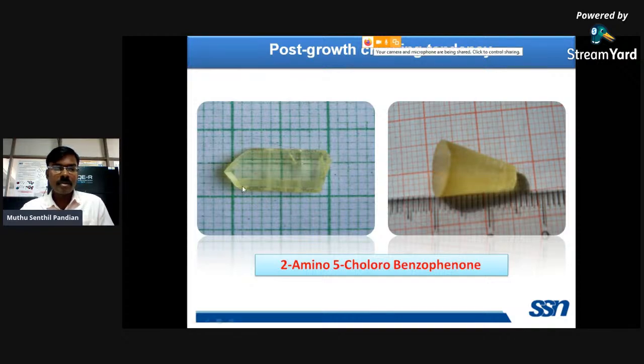So this is the 2-amino-5-chlorobenzophenone single crystal grown by the conventional method. Due to temperature instability, several micro cracks and milky opaque regions are formed in the crystals grown by the conventional method. But in the case of the SR method, we have maintained two temperatures: one at the top portion, another at the bottom portion.